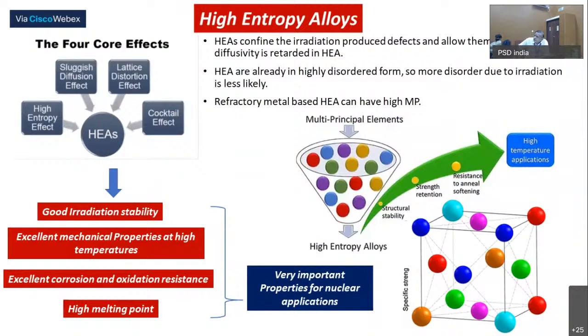Now, the point is, ordered structures, when exposed to irradiation, undergo a disorder transformation. High entropy alloy is already disordered. That is where they gain the strength, by increasing the disorder. So something which is already disordered, you cannot disorder further. That is why structural stability will be very high. Now, the third point is that suppose we have refractory metals. Refractory metals have a high melting point. If we have a high melting point, then the structure will be stable to very high temperature.